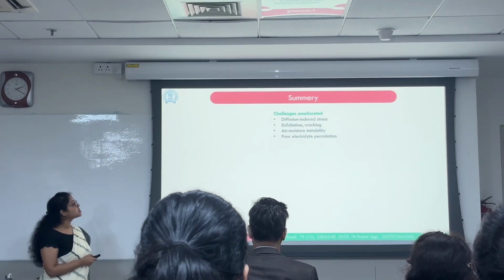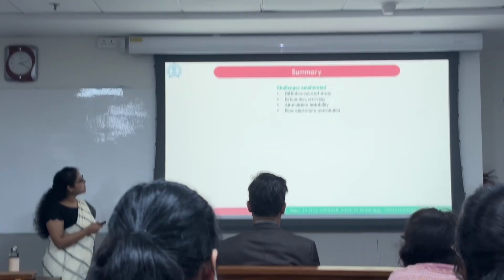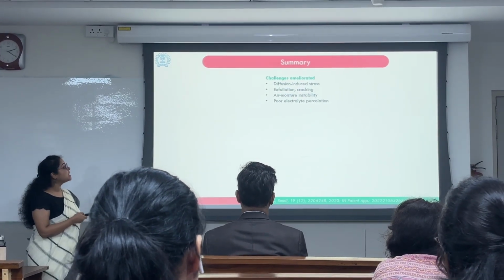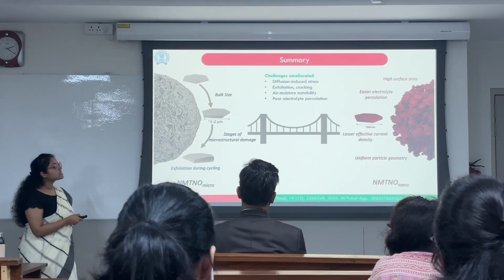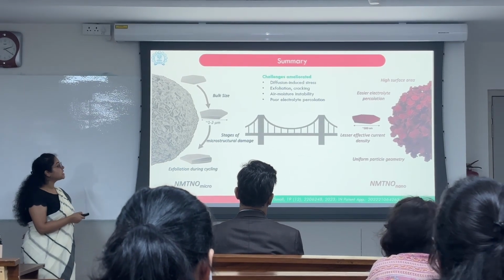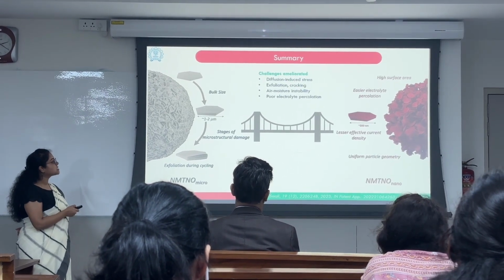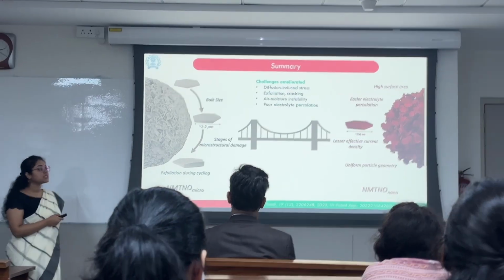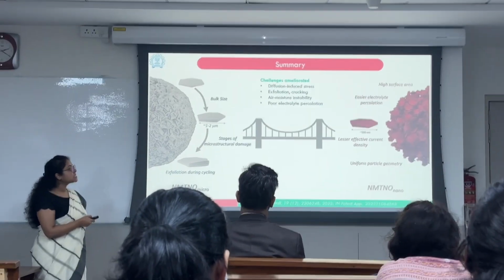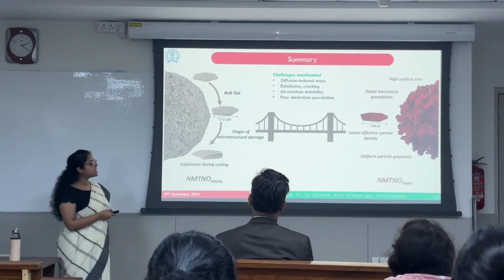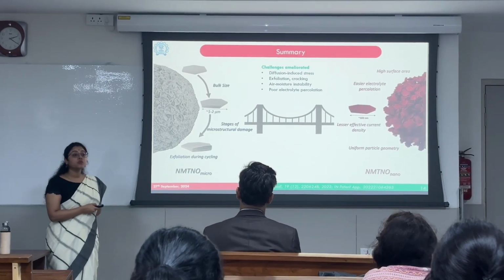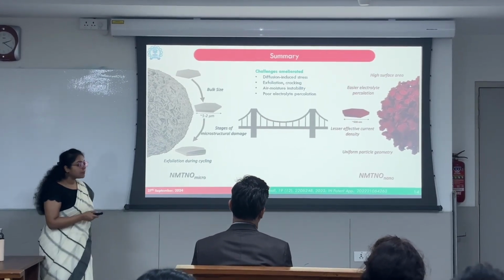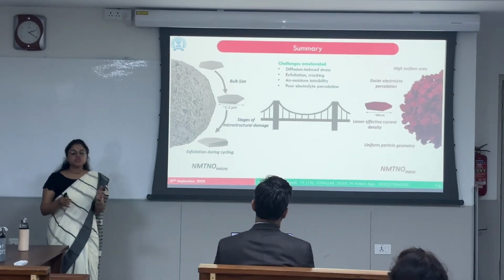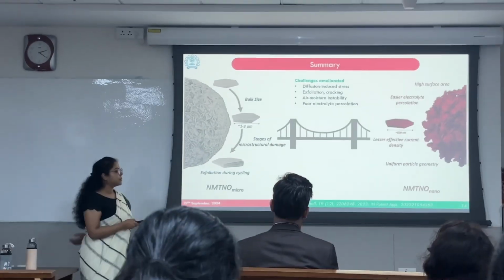Hence, in this particular chapter, we dealt with the problems of diffusion-induced stress, exfoliation and cracking, air moisture instability, and poor electrolyte percolation by making nanocrystallites of NMTNO, which, in contrast to the bulk size that suffers through stages of microstructural damage, has higher surface area, easier electrolyte percolation, lesser effective current density, and uniform particle geometry, thereby bridging the gap between the microstructure and the electrochemical properties.